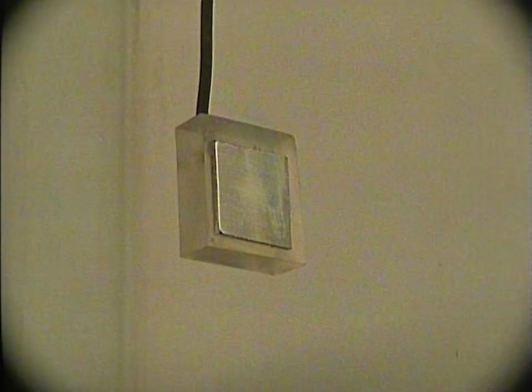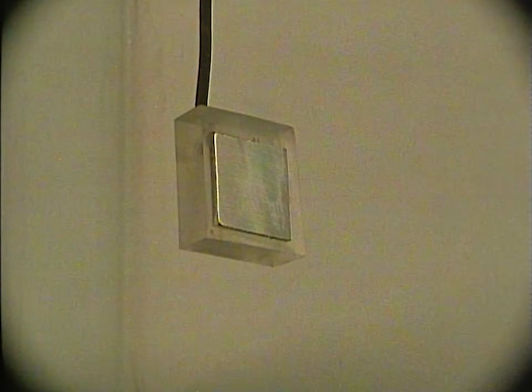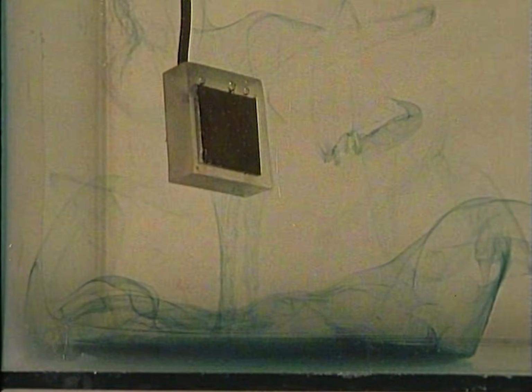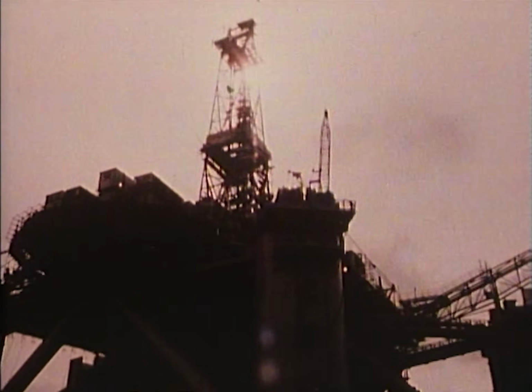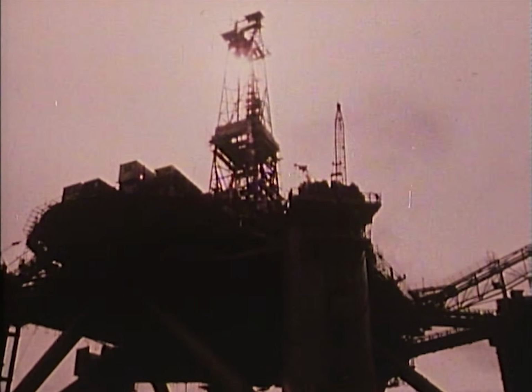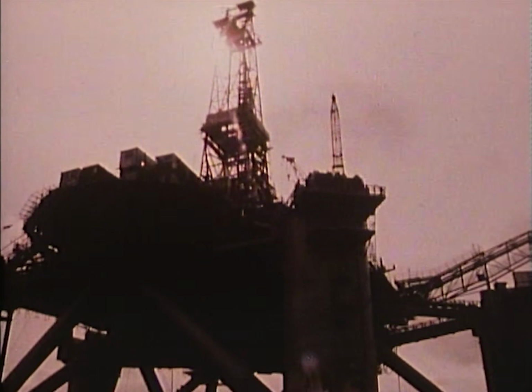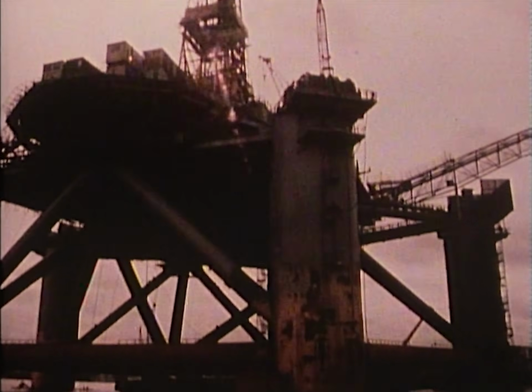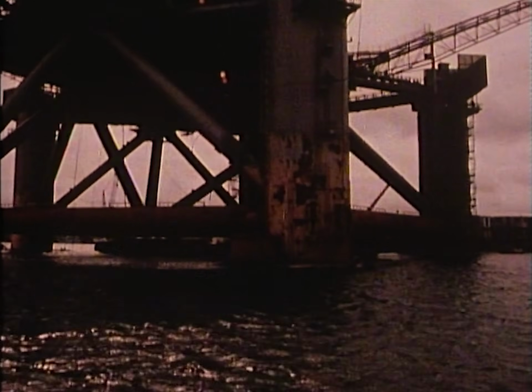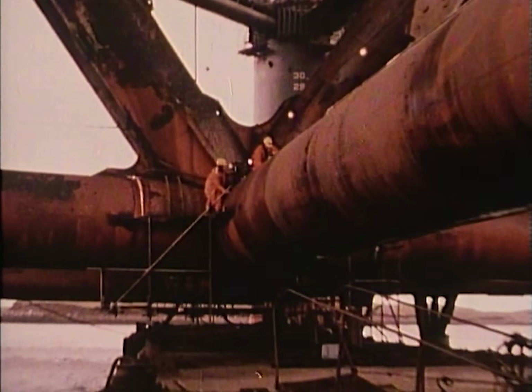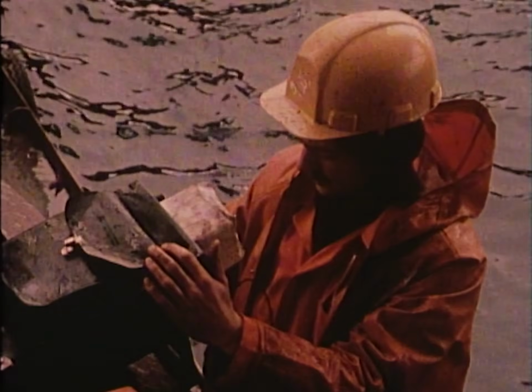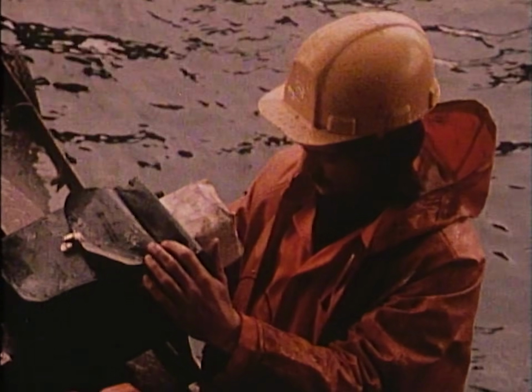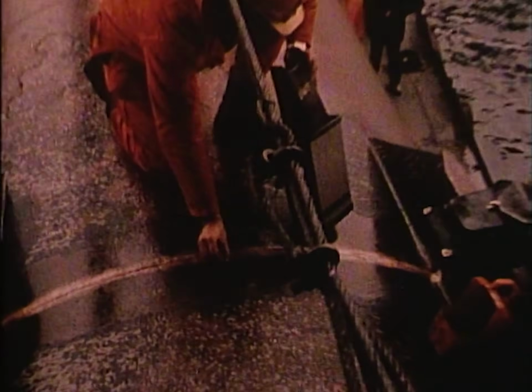This is a tiny piece of the metal used to build the rigs, mild steel, in a tank of seawater. A dye shows up any dissolved metal. Billions of times bigger, but basically no different, is this North Sea oil rig. We're not terribly concerned by simple metal loss on a structure. There is severe concern when it happens, but the killer is corrosion fatigue, which leads to perhaps catastrophic failure at a welded joint.